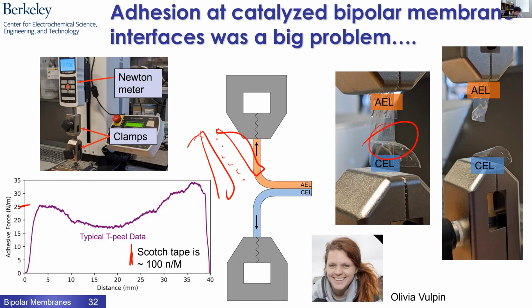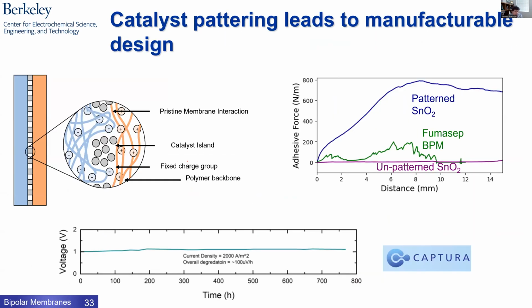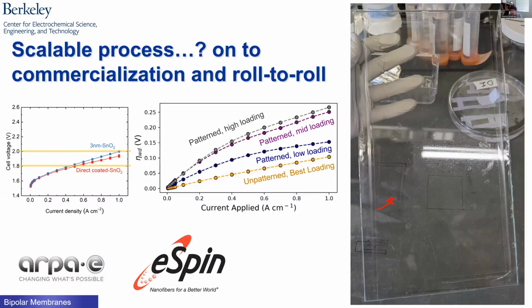Now, in our devices, it didn't really matter because we're actively pressing on them through the membrane electrode assembly architecture. So what we've done here, by developing these really active catalysts, is we're now patterning the catalyst and leaving some unpatterned area, and this gives us really high adhesion. So this is actually 4 times higher than even the commercial membranes now, along with this 20 times lower voltage. And these are really stable, also measured by other companies that are interested in using this. So this is what they look like, optimizing all this. This is just made in our lab, but we're passing this off to a couple companies that are commercializing this. And you can make big membranes, pattern the catalyst, and they really work well.